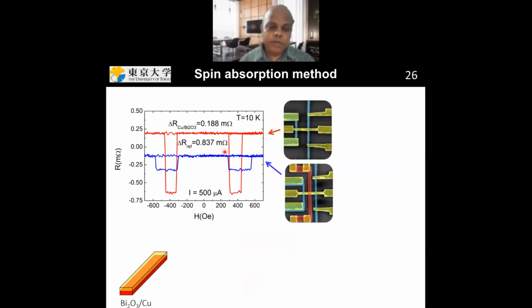After making the device, you have to measure. This red curve shows the spin signal of a simple non-local spin valve device, and this blue one shows a device in which there is bismuth oxide copper in the middle. You can see that the spin signal is reduced because some of the spin current is absorbed by this bilayer.